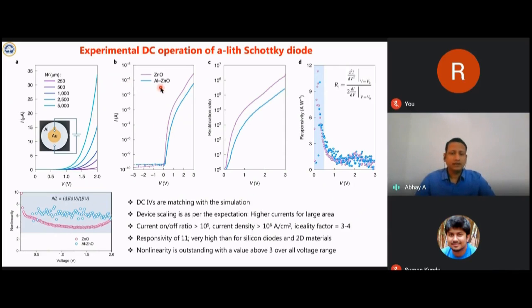So here we use two different types of zinc oxide. One is intrinsic zinc oxide, which is shown here in the violet region, and aluminum doped zinc oxide, which is here in the blue color. Both forms of zinc oxide are well-known materials, but there is one particular reason which I will tell you in the next slide. So this rectification ratio is plotted as a function of bias voltage, and of course this zinc oxide shows a little bit larger rectification ratio, but both devices show rectification ratio above 10^5, and that is important.